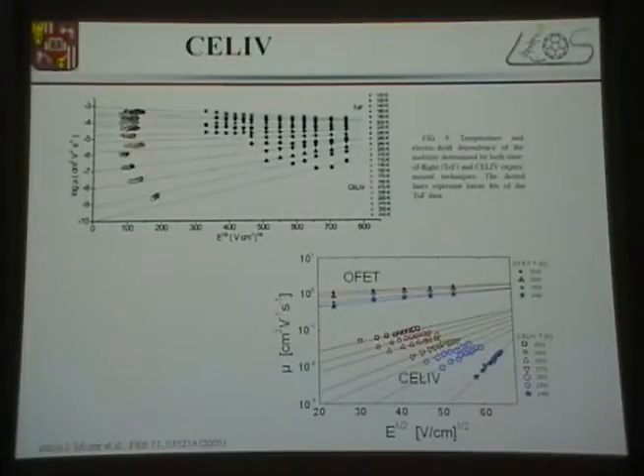The nice work we've done with Attila, when we tried to measure the mobility as a function of electric field, and this is a nice work where Attila showed that it's a very nice agreement between CELIV and the time of flight data. It also covers the broad electric field range. It also gets negative mobility, but I won't go into the detail. This is a whole separate discussion. You can spend another hour on that.